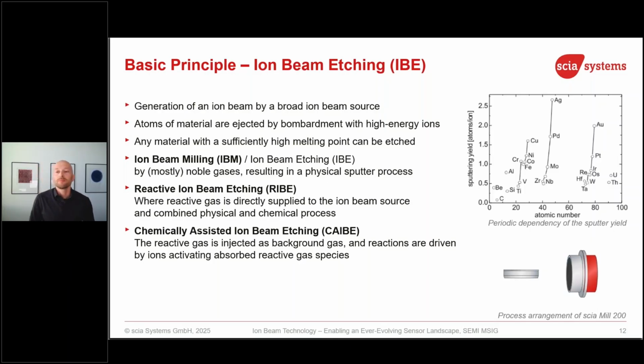Usually you don't get a great selectivity for ion beam sputtering. In the right graph here, we see a lot of different elements by atomic number, and for argon it's shown how the sputter yield is changing. Carbon is etching very slowly, and silver and gold are sputtering very fast, but most of the elements are basically in the same order of magnitude regarding etch rate. Only if we introduce chemistry can we get a nice selectivity. Additionally, in our system, we have a substrate holder which is able to rotate and to tilt. This tilting allows us to change the angle of incidence. This will be shown later, how this can affect sputter yields. And there are some other positive side effects here.